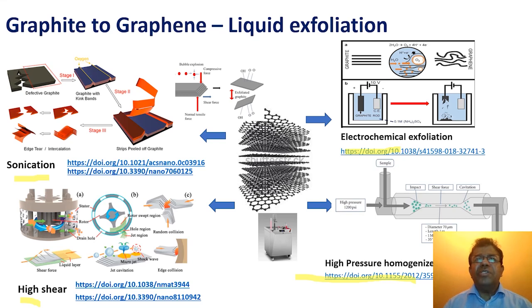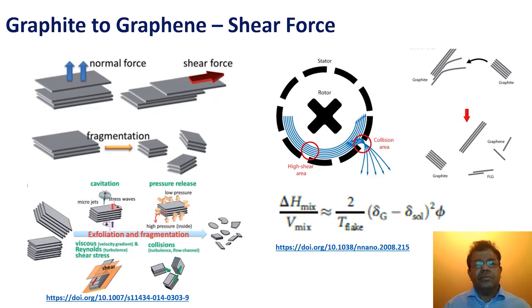Besides, many molecules such as surfactant molecules and polymer compounds are used as exfoliation agents to generate new forces such as pi-pi conjugation, hydrophobic force and Coulomb attraction, and match the surface energy of the graphene layers to that of the exfoliation media. The underlying scientific principle is similar to Griffith theory of crack propagation. Reduction in potential energy should be greater than or equal to an increased surface energy due to the creation of a new free surface. The excess energy exerted by the chosen exfoliation technique can also fragment large graphite particles or graphene layers into smaller ones.